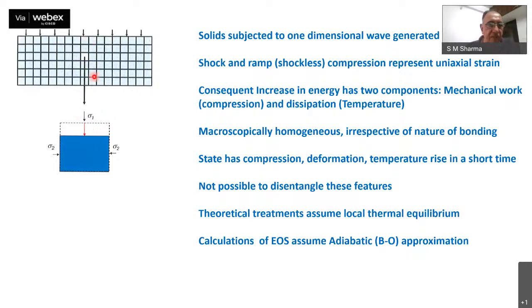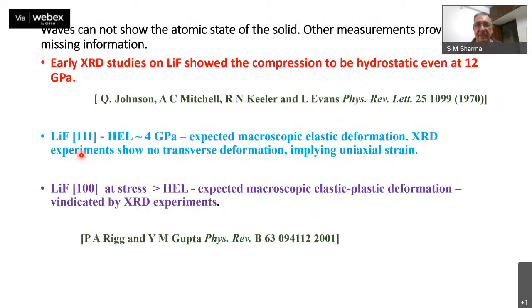So therefore, the uniaxial strain state cannot be indefinitely retained. Questions have been asked whether a uniaxial strain state exists at all. And the reason it was doubted was, way back in the 70s, experiments by Wackerle, Johnson, Mitchell, Keeler and Evans showed through flash XRD studies on lithium fluoride, shocked to 12 GPa, that the material only showed hydrostatic compression, which means that there is no uniaxial compression in this material. So lots of discussion took place subsequent to that, on how a material evolves from a uniaxial strain state to the hydrostatic state and so on.